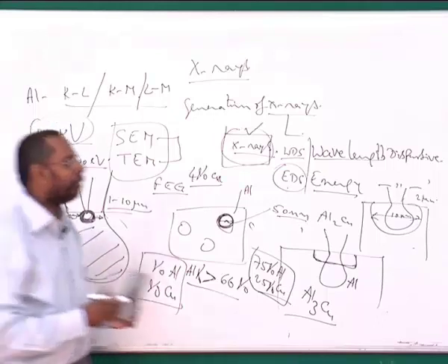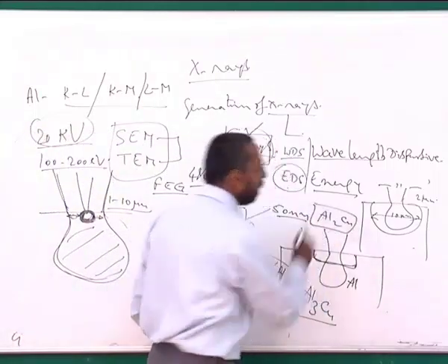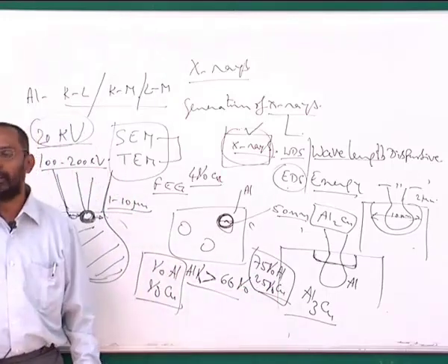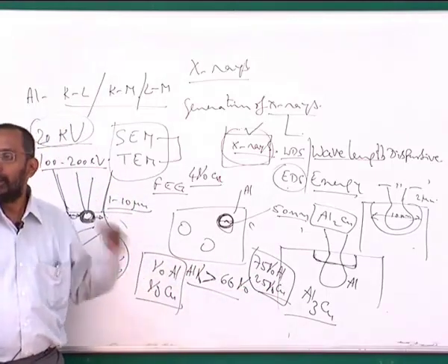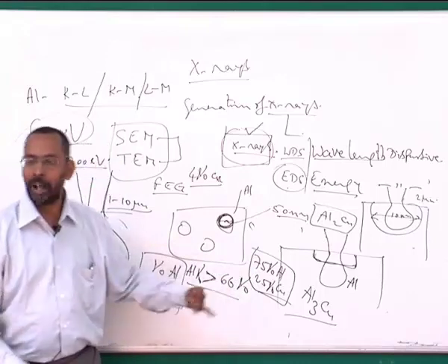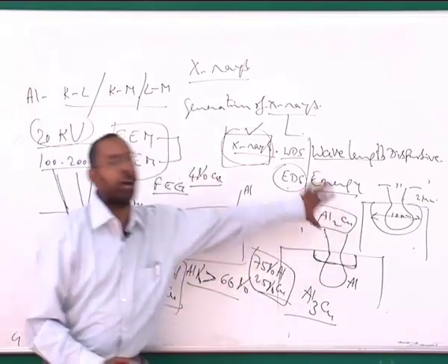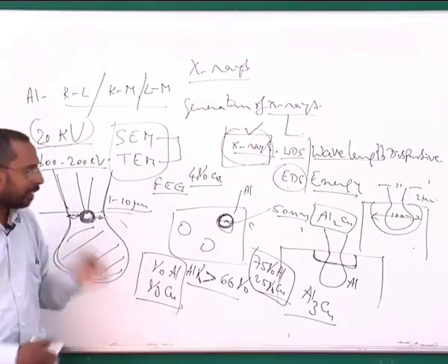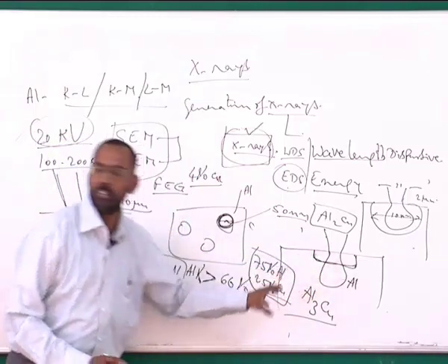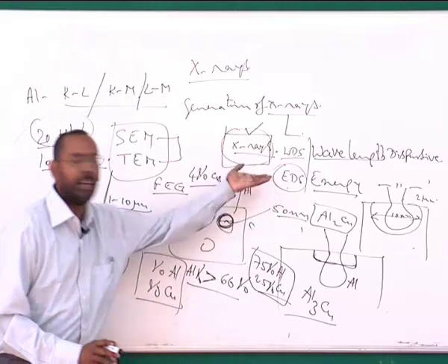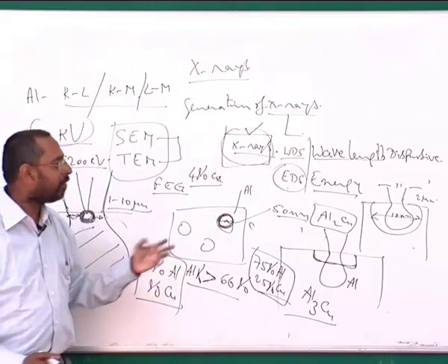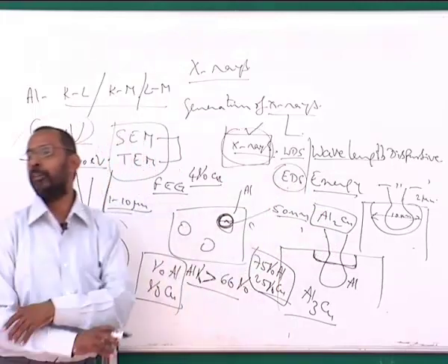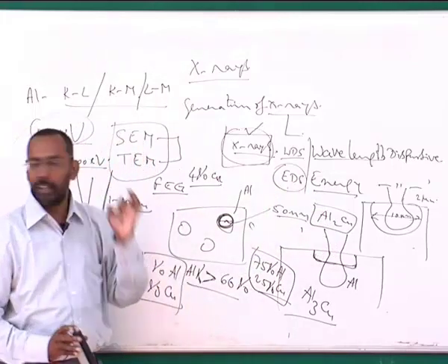And if my phase diagram shows that only Al2Cu is possible, but I am seeing an Al3Cu kind of composition, then I should understand that this difference is coming because some of the matrix is also contributing to my composition. As a result, because the matrix is mostly aluminum rich, the aluminum content of the particle appears higher. It appears the beam is falling on the particle, but I am not actually measuring the composition of the particle. So this is very, very crucial.